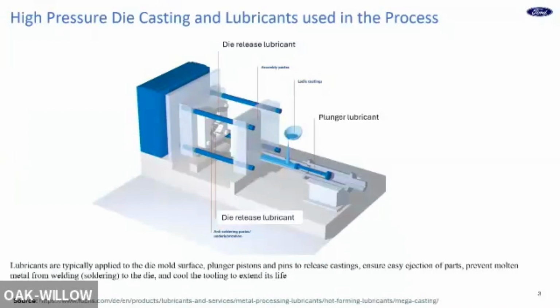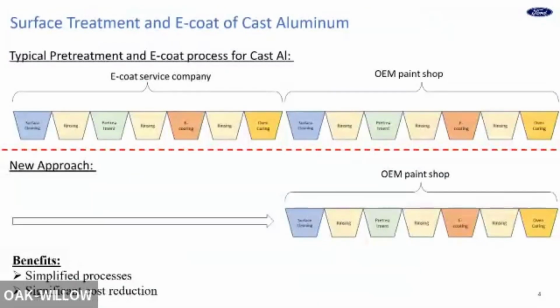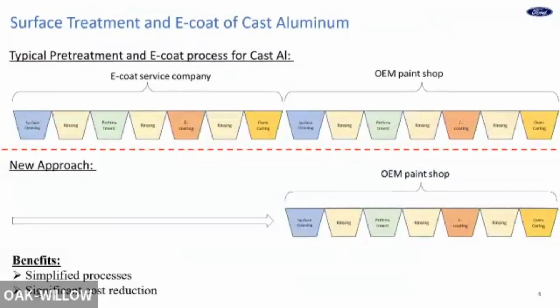on the surface. After the casting process, the part may be machined or trimmed, so there can be some coolant or lubricant. So the casting must be cleaned and sometimes requires pre-treatment and E-coat. One typical pre-treatment and E-coat process is that we send the part to the E-coat company, and they do the cleaning, pre-treatment, and E-coat and cure. Then the E-coated part is sent to the OEM body shop. It can be assembled with other metal substrates, then pass through the paint shop again.